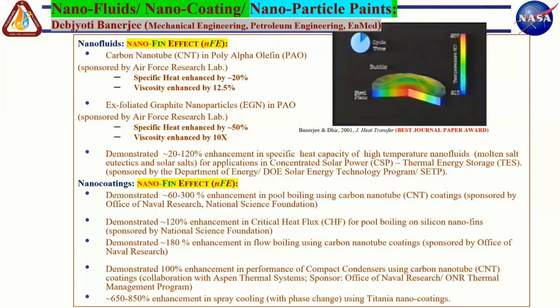But not only that, polyalpha olefin, which is a Newtonian fluid, started behaving like a non-Newtonian fluid once you added nanoparticles to it. And the viscosity enhancement could be anywhere between 10% to all the way 10 times enhancement in viscosity, depending on the temperature range in which you operate.